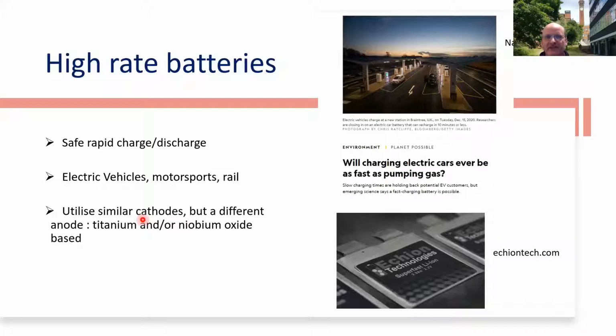And one of the biggest challenges regarding rapid charge is actually the graphite. What will happen with graphite if you rapidly charge? The lithium will go initially between the layers, but if you try and charge too fast, you start to plate lithium. So you put lithium metal on your anode, and that will potentially cause you safety issues. So the limiting factor of a conventional battery in terms of fast charge is mainly that graphite. And so that's why there's this interest in alternative electrodes.